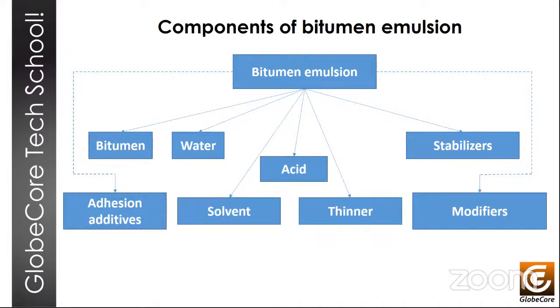Stabilizers are used to reduce the changes in the physical and chemical properties of the emulsion during storage and use. That would likely be something like 0.05 to 0.1% of a 30 to 35% calcium chloride solution by weight.